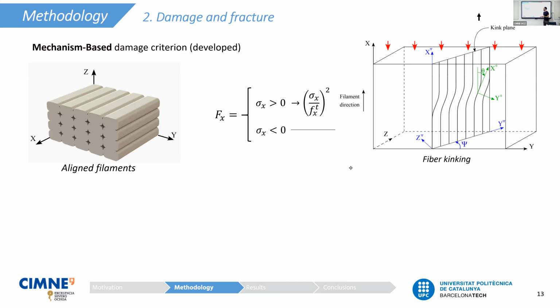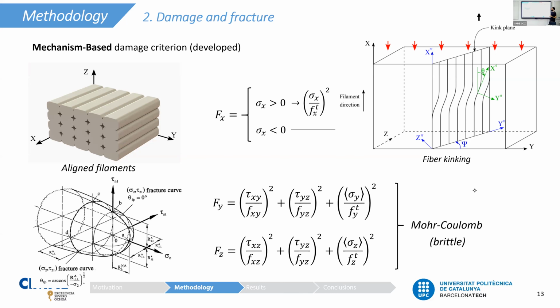If the filaments are under compression, a buckling occurs. More specifically, a phenomenon called fiber kinking occurs that is slightly more complex than a buckling, but in the end is driven by that phenomenon. And therefore, we use another different formula. And for the y and z direction, since it is a brittle type of fracture, this failure mode would be due to the decohesion between either adjacent layers or adjacent filaments. We use a Mohr-Coulomb failure criterion that is normally used for brittle materials.